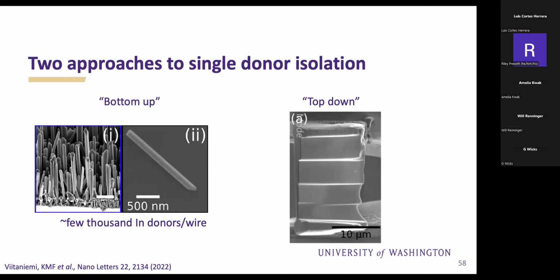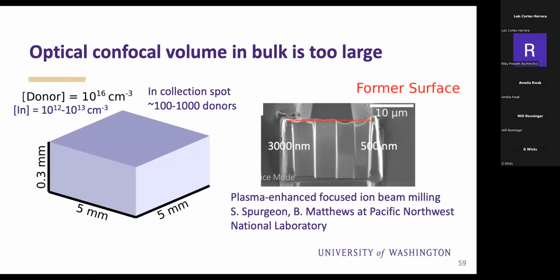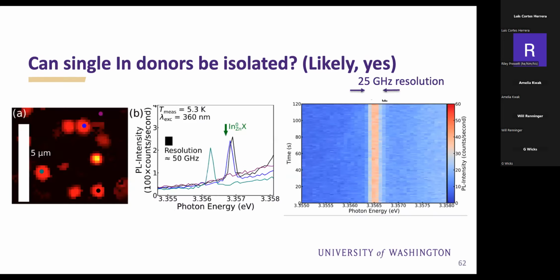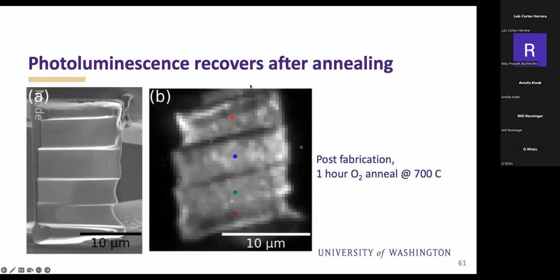This is something that would not work in diamond. It turns out if you use focused ion beam in diamond, it causes too much damage and you won't actually be able to observe the NV photoluminescence. But we thought we'd try it. Zinc oxide's a different material. And if we move forward, sure enough, this is the sample.